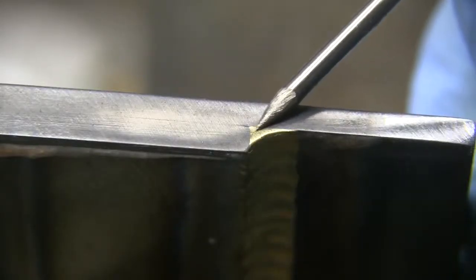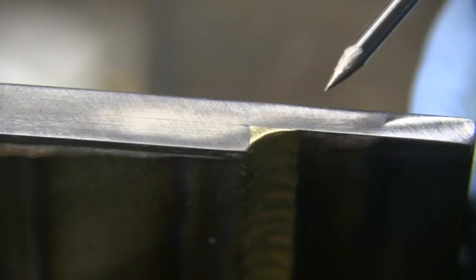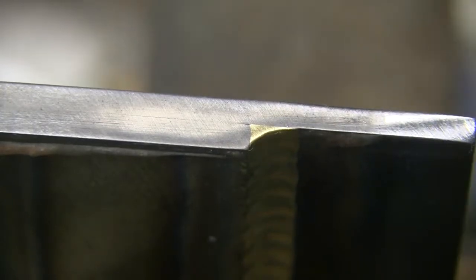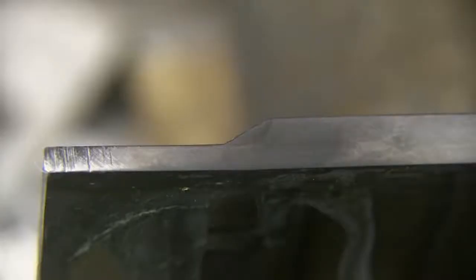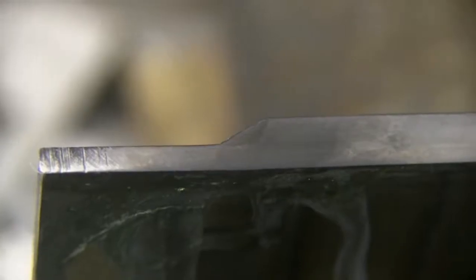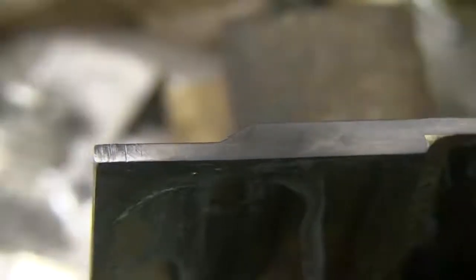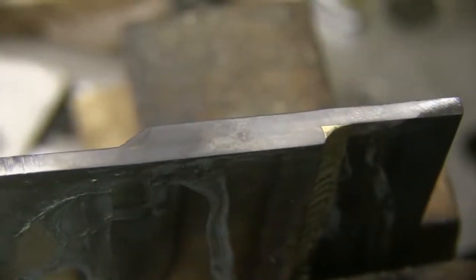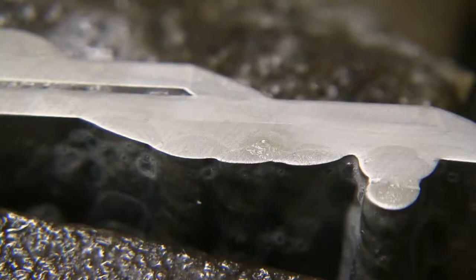Alright, now there's the cross section of the aluminum bronze TIG braze joint. You see it basically looks like a braze joint. No depth of fusion at all. It flowed in there. It's at right angles. Unlike the ER70 weld joint here that has a nice weld nugget profile where it penetrated, melted the corner off a little bit because it's a weld, and the other one is a braze.